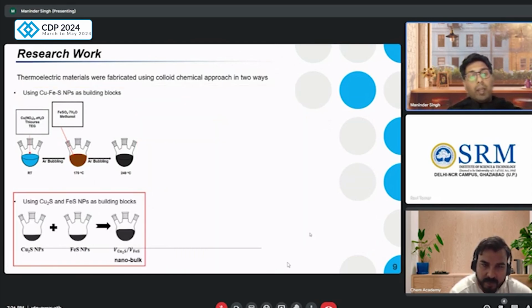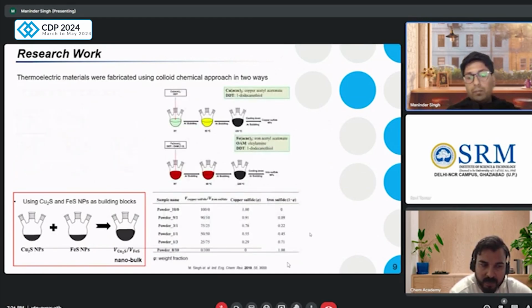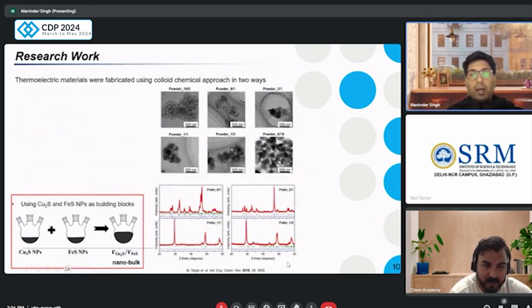And in the second part of what I did, I created copper sulfide nanoparticles separately and iron sulfide nanoparticles separately, and I mixed them in different ratios. I created almost 5 samples, and you can see very good spherical particles here. But when I inserted iron into it, you can see the particle size changes. So inclusion of a different kind of element can change the shape and size of the nanoparticles. So this is very important. Before studying any nanoparticle and its properties, you should learn that the nanoparticles that are formed have a certain effect on the end product and the properties related to it.